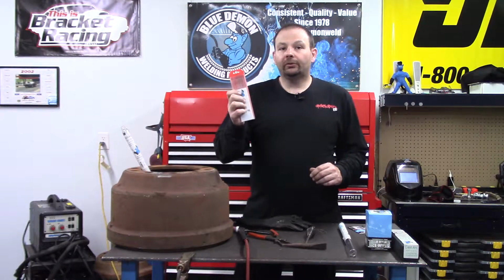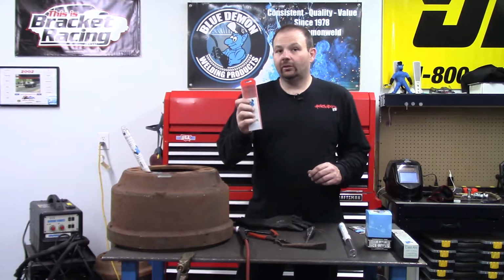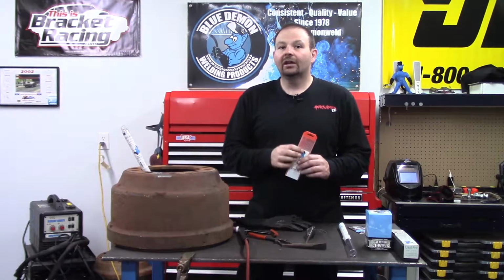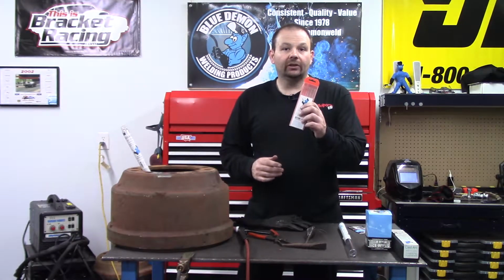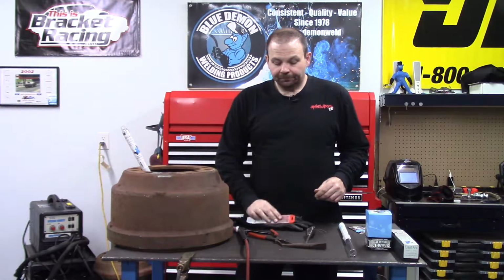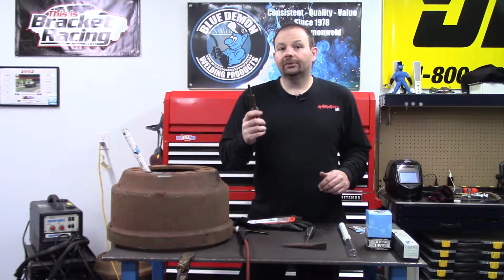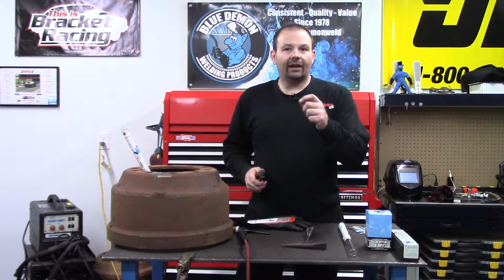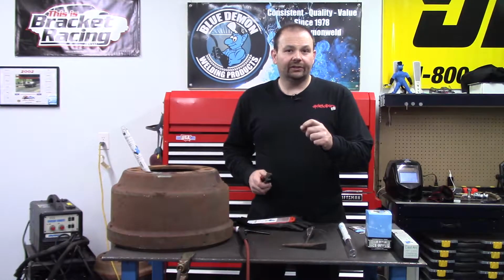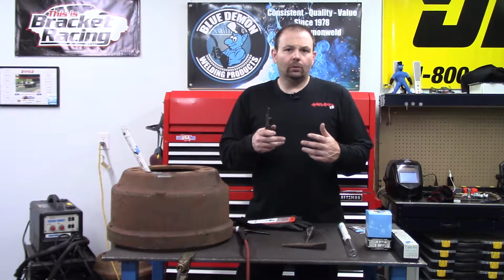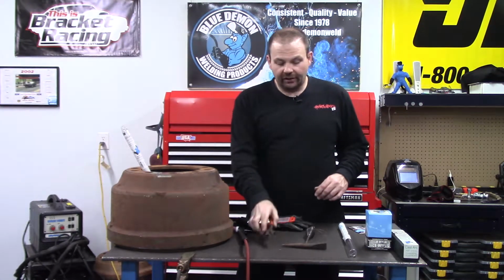During that process, I learned that 2% thoriated tungsten is definitely the way to go. I tried a couple of different tungstens. They did not work as well as the 2% thoriated, by far the best option to go with. Something else you're going to need is some welders' cutters to cut those oxidized ends off. I noticed as I would fire back up, if I used the oxidized end, the weld pool was a little sluggish and had a lot of stuff floating around in it, which is not good. So make sure you cut those ends off.